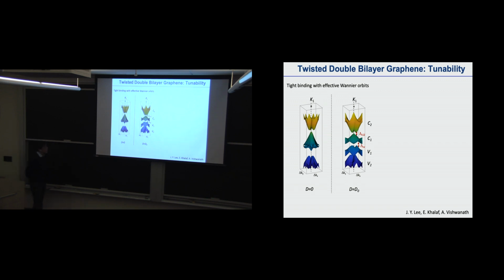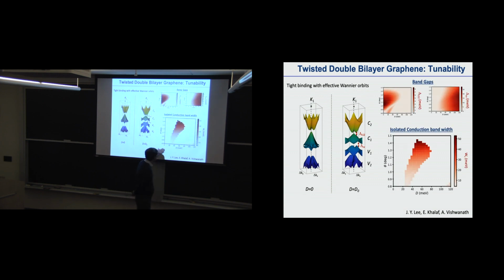What angle ranges? We had great support from Ashwin's group in-house, and they gave us the range of angles expected, and what displacement field to use. You get this flat, isolated band, which is basically the basic ingredient we expect to see for the strongly correlated gap opening in the single particle band. Based on this math, we chose somewhere around 1.3 degrees, and we can tune this displacement field and ask what is going to happen.